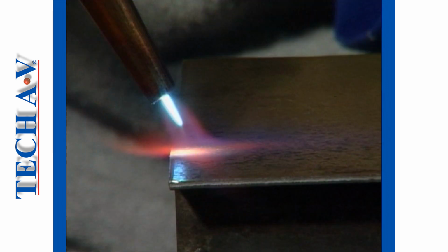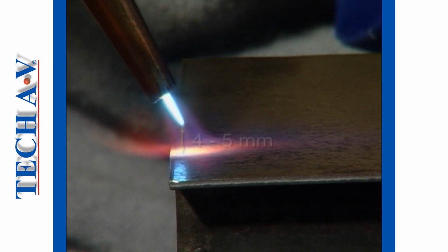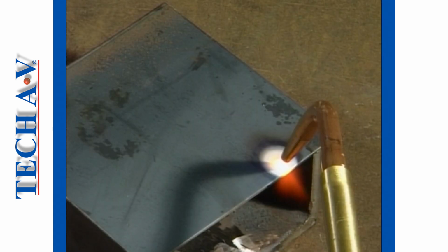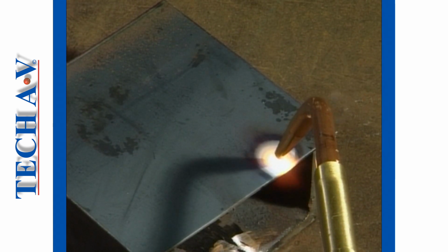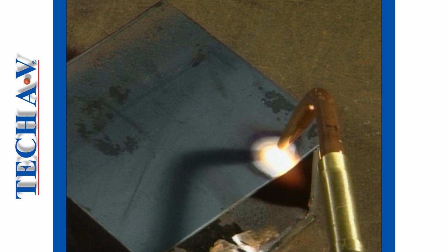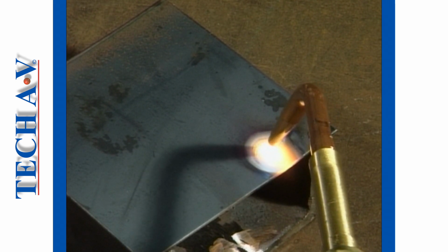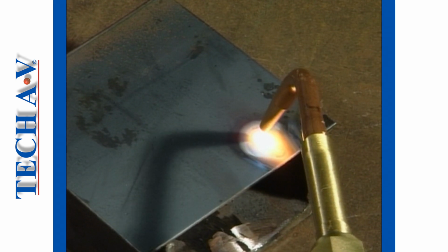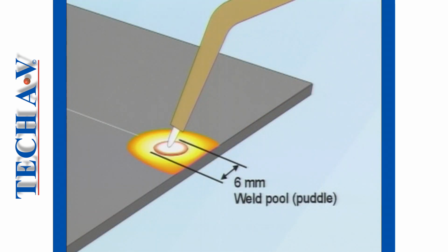It is important that you keep the flame at the correct distance from the plate. The cone should never contact the weld. Maintain a distance of about 4 to 5 millimeters between the cone and the surface. Set up a small oscillating movement of the nozzle, either by rotating a little circle or a slight side-to-side action, as you apply heat to the plate. The object here is to create a pool or a puddle of molten metal about 6 millimeters in diameter, and keep this pool moving along the metal.